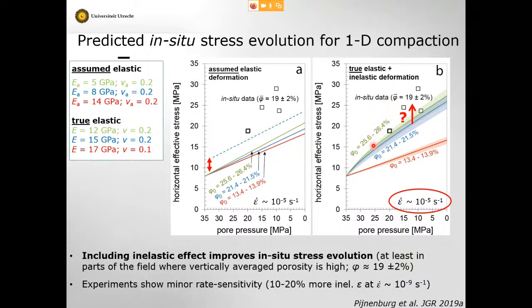If you take this inelastic behavior combined with true elastic, so our constitutive model, what you see is that samples with the higher porosity, above 20%, show much larger horizontal effective stress development, which corresponds a lot better with the measurements in the field, which incidentally come from a region where the sandstone has a porosity of 19%. So what we believe here is that our results are giving a much better constitutive description of the way the sandstone behaves, and so that model should give a better description of the stress-strain evolution in the reservoir around faults as depletion occurs. So it should be a better basis for modeling the behavior of the sandstone.